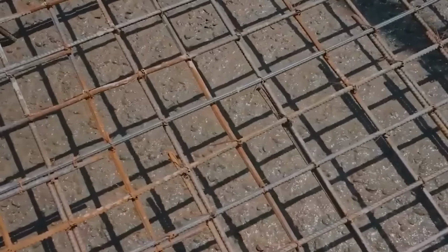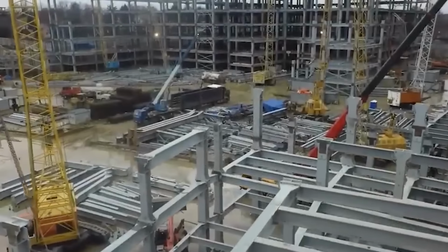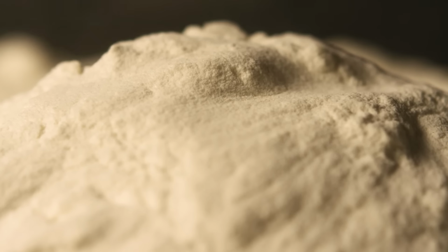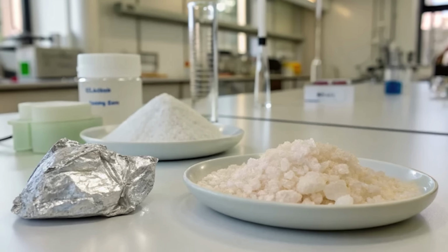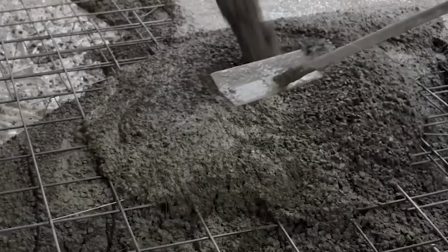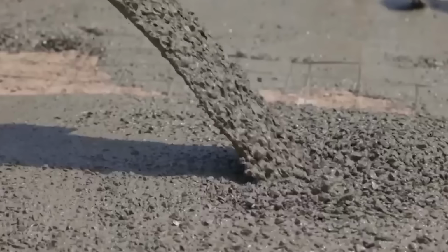Here is the mechanism itself. Fly ash and ground granulated blast furnace slag both contain silica and alumina, locked inside a glassy, largely unreactive structure. On their own, mixed with water, they do almost nothing useful. Introduce a strongly alkaline activating solution, typically sodium hydroxide combined with sodium silicate, and that glassy structure dissolves at the molecular level. The freed silica and alumina then reassemble into a dense, three-dimensional aluminosilicate network, chemically distinct from the calcium silicate hydrate structure that ordinary cement forms, but mechanically similar in the job it does. It locks everything into a rigid, load-bearing solid.